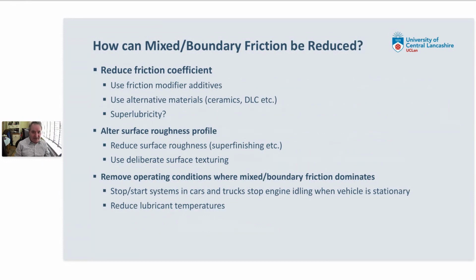So we've seen that there are some very large numbers here on how much fuel is used to overcome mixed and boundary friction, what that means financially, and how much CO2 emissions there are. So there's a lot of interest in the tribology community in how to reduce mixed and boundary friction. And there are really three main approaches. First of all, we could try and reduce the friction coefficient between the moving surfaces. So we can use friction modifier additives in lubricants. We could look at using alternative materials, such as ceramics and DLC. And there's a lot of research going on in tribology labs looking at superlubricity. Can we make changes to the surfaces so that you almost get an order of magnitude reduction in friction coefficient by making the surfaces super lubricious?